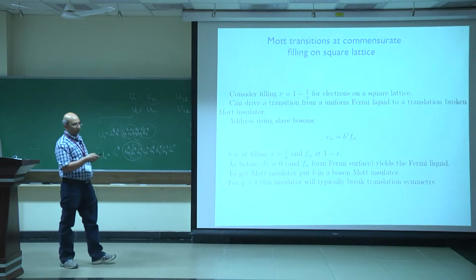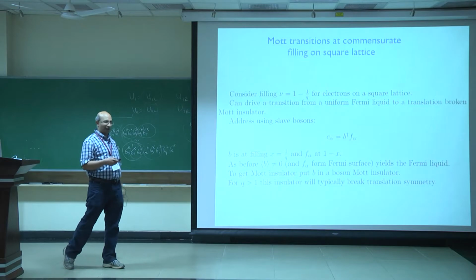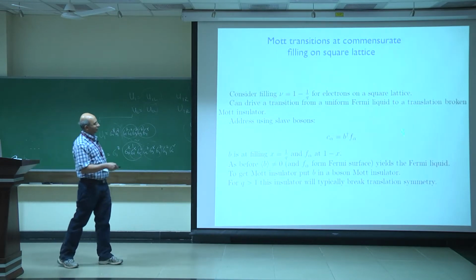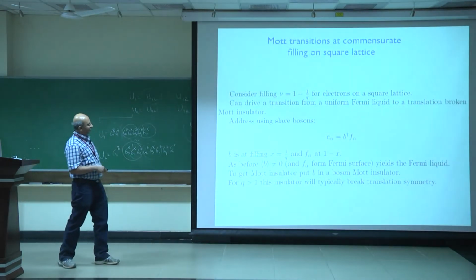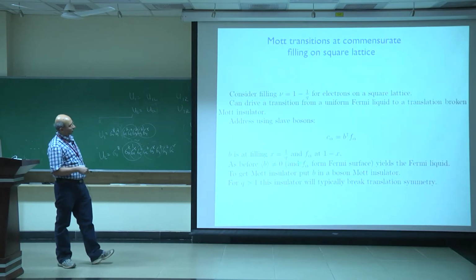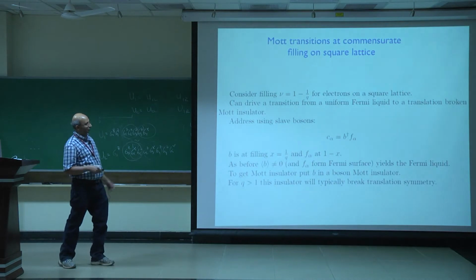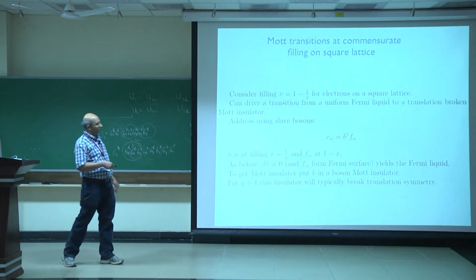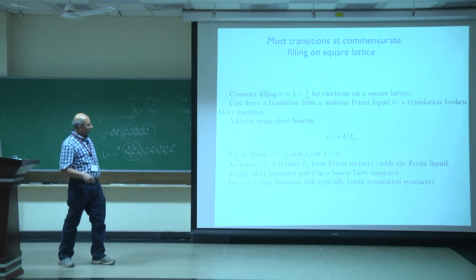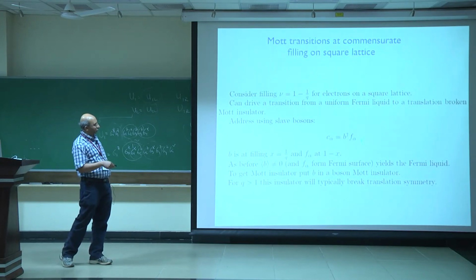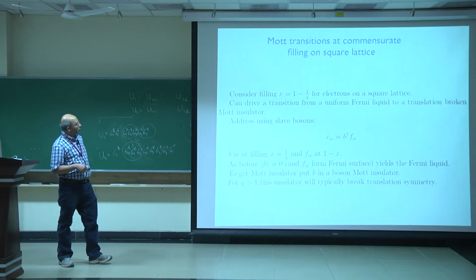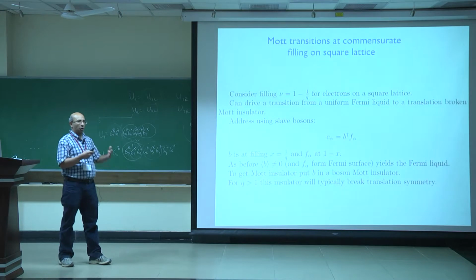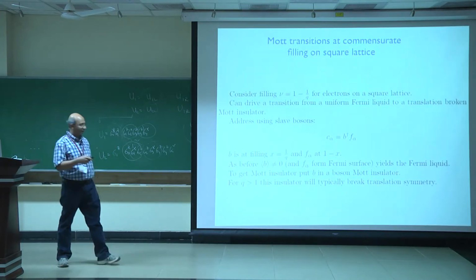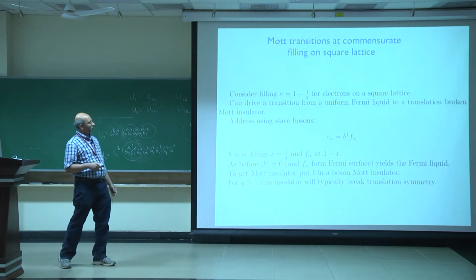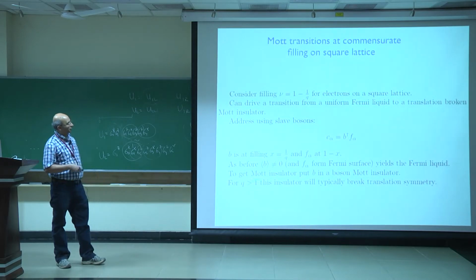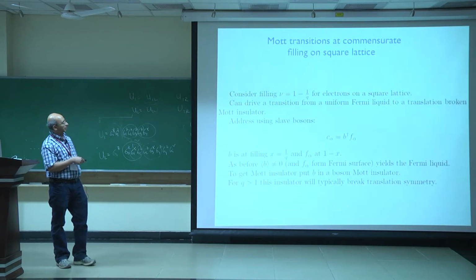And again, not being very imaginative, I'll just try to repeat the success of half filling by using a slave boson approach. So let's try to use the slave particle approach, write c alpha as b dagger times f alpha. Then the boson is at filling x equals 1 over q, and the fermion is at filling 1 minus x. As before, if the boson condenses, I can form a uniform Bose condensate, and f forms a Fermi surface. That will yield a Fermi liquid at this density. And as before, to get a Mott insulator, I must put my boson in a bosonic Mott insulator. Now, so long as q is bigger than 1, I'm at some commensurate filling, but it's not the filling at which the bosons can form a nice translation invariant insulator. This insulator will typically break translation symmetry. Okay? So this kind of Mott transition addressed within this framework will give me a transition from a uniform Fermi liquid to a translation broken Mott insulator.